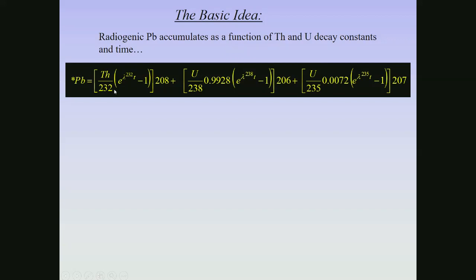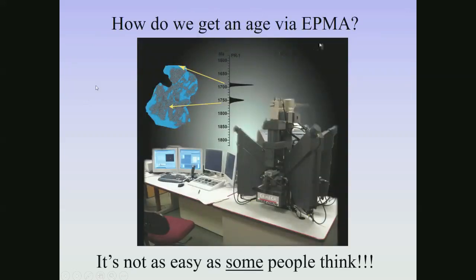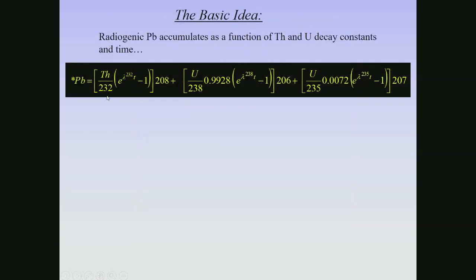The problem is that with electron microprobes, you cannot do this. So there's an implicit assumption that all of the lead is radiogenically derived from the parents, with no incorporation of common lead. For really old Proterozoic and Archean minerals such as zircon and monazite, that's not a problem, because the amount of radiogenic lead would be so much greater than the common lead incorporated that the common lead makes virtually no difference in the overall lead budget. So I would say the electron microprobe technique is only something you might consider applying for really old Proterozoic or Archean rocks or shear zones.